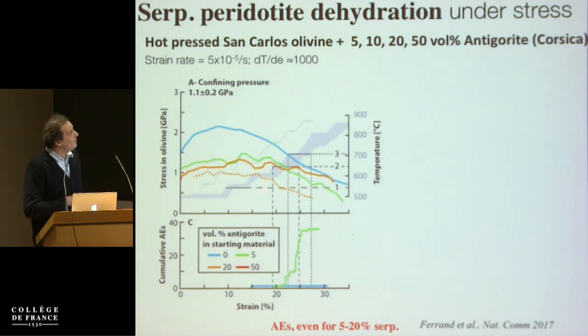But at the moment you cross 500 degrees or somewhere here, basically you see that at least for the 5% starting material, you record around 40 acoustic emissions, which are proxies for laboratory earthquakes, and I will come back to that.